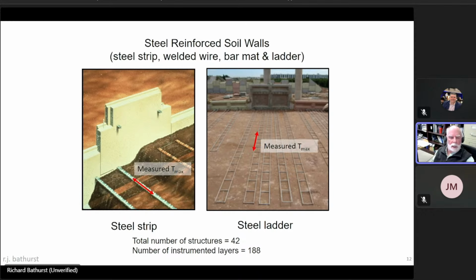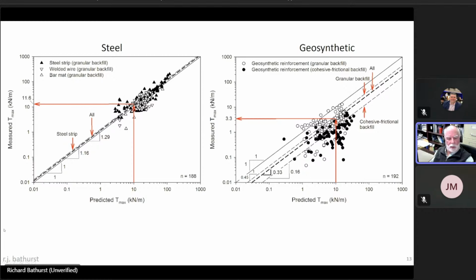And it was interesting because when we did the same exercise on the left-hand side here of plotting measured loads against predicted loads, there was arguably reasonably good correspondence. And what we figured out was that when these design methods to calculate the design loads in these reinforcement methods, the method was actually empirically adjusted against measured loads, and this improved the accuracy of their load prediction models. But when the simplified method was originally invented, there were no instrumented structures that could give us measured loads so that we could empirically adjust the model to give better predictions.